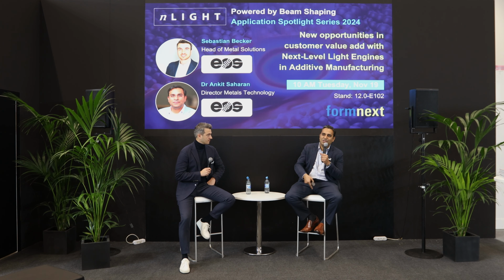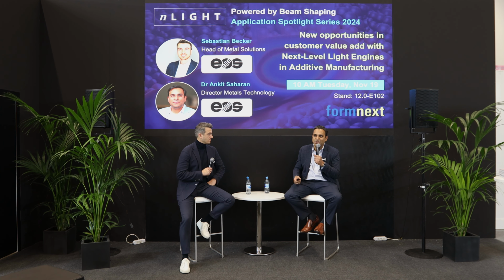So I think that's the added benefit at the end of the day: how to better manage thermal stability, like Sebastian said, and get better melt pool characteristics. What we're trying to do is not go deeper. At higher power, you go deeper into the melt, like deeper welds into the pool, and the deeper you go, the more keyholes you form. We're trying to come to conduction welding as much as we can, so trying to stay at the surface and not have as much porosity.